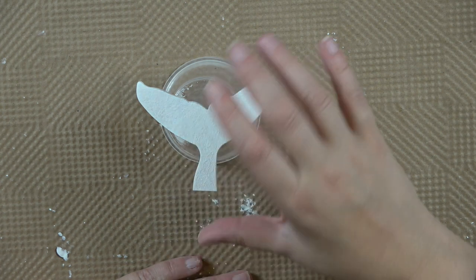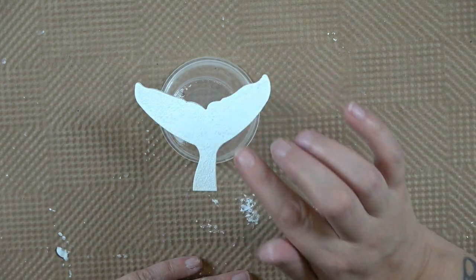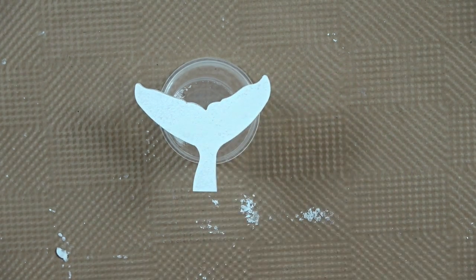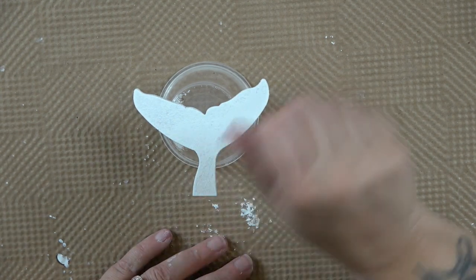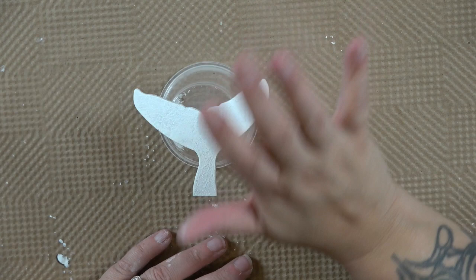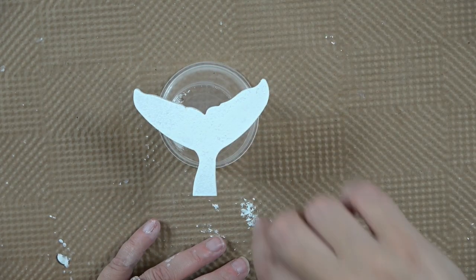The other thing is, if you get this dry and you can see through to the clear glass, you've probably mixed the enamel too thin, or you don't have enough enamel. So don't just keep putting more on. Okay, dry that first coat. It literally takes about 90 seconds with a blow dryer, and then add more. Otherwise, you're just pulling up wet paint.